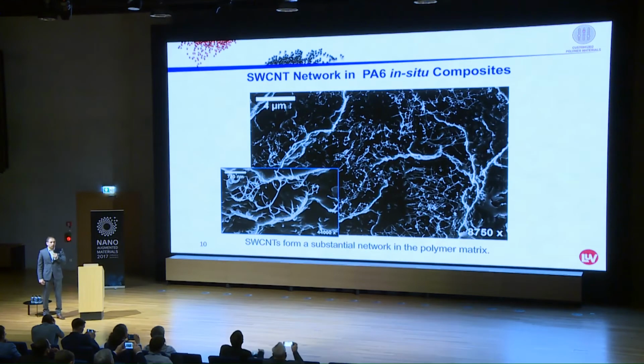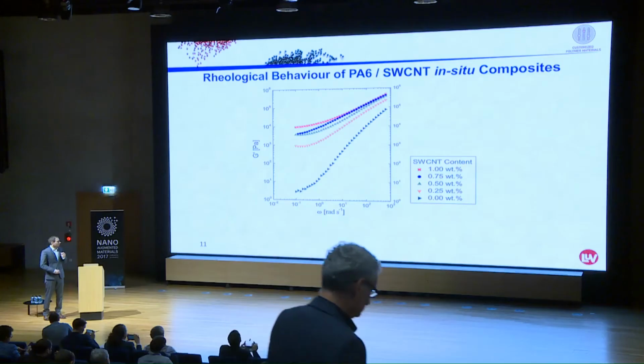Here is an SEM picture, and we can see that we have all these tiny lines in the polymer matrix, these white lines, the really small ones, not the big ones. The small lines, this network here, is formed by TUBALLs over the entire polymer. We can imagine that this will have a big effect on the property profile of the material, and this is what we want to achieve.